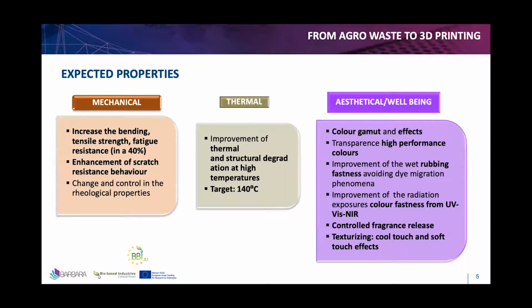The expected properties of the BioBarr products were to obtain an increase in the mechanical properties of 40%, specifically when dealing with bending, tensile strength, and fatigue, but also enhance the scratch resistance behavior. When we talk about thermal properties, the target was set out by the construction sector in achieving at least 140 degrees Celsius, which was key and strategic for the application, the mold. And finally, more focus in the automotive products were good requirements, or key requirements, to get a broad color gamut, enhance the fastness of the natural colorants into the polymer, and also to be able to obtain different textures and even introduce a customized fragrance.